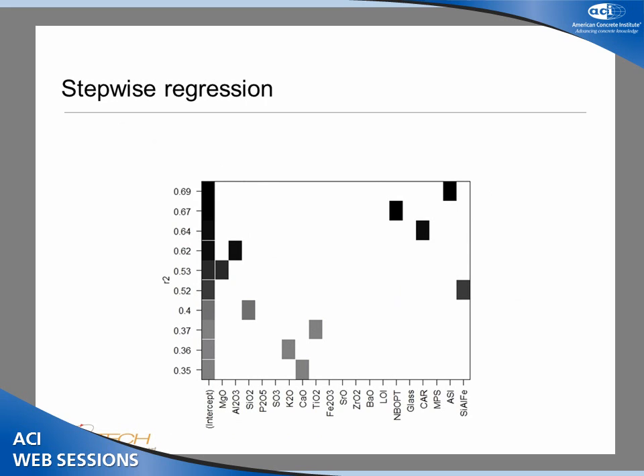So what we did was to run a stepwise regression. Basically, we took all the possible regressors: the oxides from the chemical analysis, LOI, non-bridging oxygens per tetrahedron, the amount of glass. We also considered the calcium to alumina ratio, the mean particle size, the alumina saturation index, and the sum of silicon plus iron plus aluminum. As you can see here, on the y-axis is the correlation factor, R squared, and on the x-axis, what I just told you. The alumina saturation index came out to be one of the main parameters that influences the compressive strength, followed by non-bridging oxygens per tetrahedron and the calcium to alumina ratio.